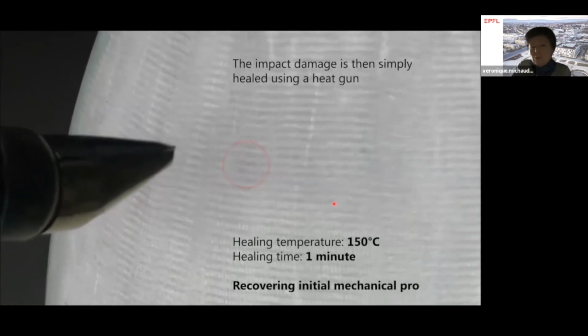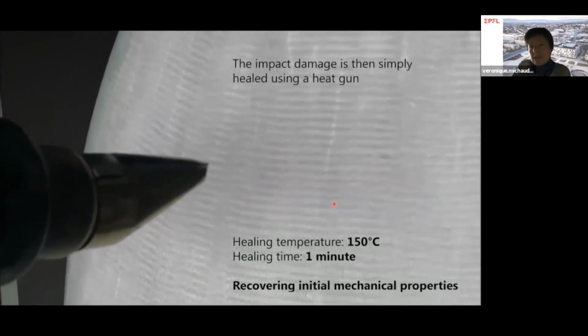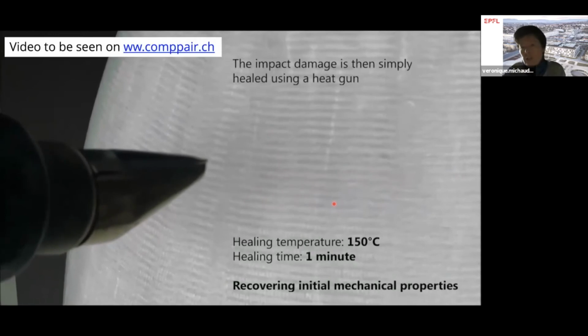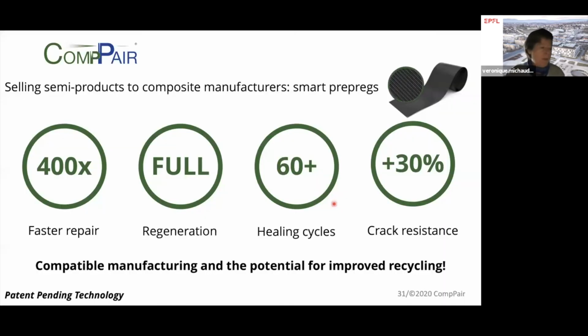Looks like magic almost. And we check, of course, that we recover the initial mechanical properties, and also there is no real change on the surface, for example, quality of the part and so on. So with this, we went on to create a company after we had filed this patent, which is called CompPair, making semi-products for composite manufacturers, which are pre-pregs in this case. So we moved from infusion to pre-pregs with a 400 times faster repair than, of course, having to send a guy, having to cut and do all the repair that would normally be done. Good regeneration, we can do a lot of healing cycles, and we have also an increased crack resistance compared to a decent usual resin that people would use.